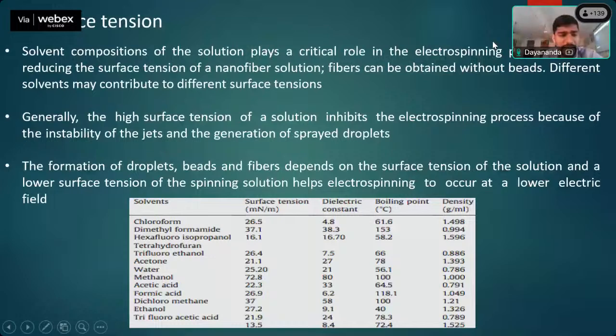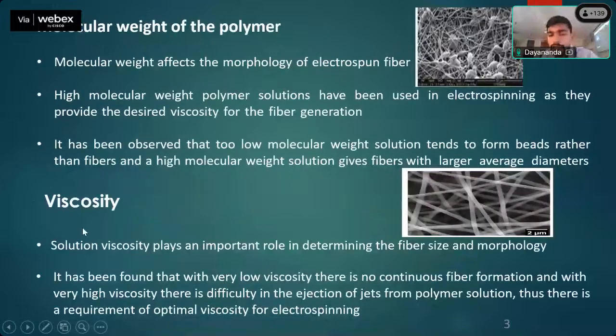Next one is the viscosity, and viscosity also decides the morphology. If the viscosity of the polymer solution is very high, injecting the polymer solution through the needle will be extremely difficult since the solution will be too thick. It is found that at very low viscosity there is no continuous fiber formation - you can get fiber formation, but it will not be continuous. So while preparing the solution, the viscosity also has to be optimized properly.